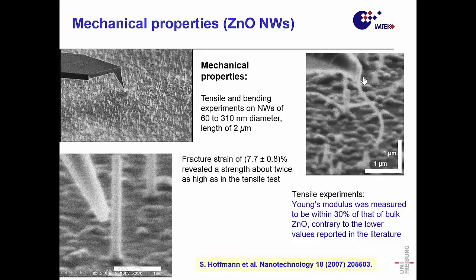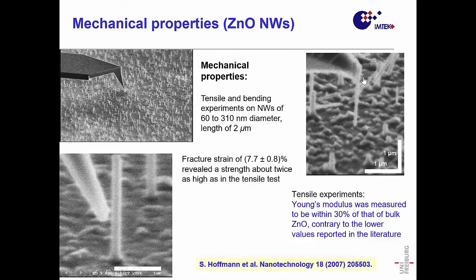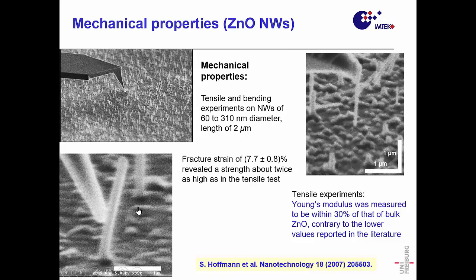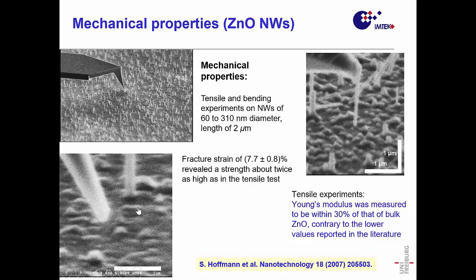And just remember, it's a single crystalline nanowire. It's, I think, amazing. By doing this experiment and then a video clip of that, you can actually then calculate the mechanical properties of these nanowires. Please take care to also keep in mind that your tip has mechanical properties. And so what we measured is that the mechanical properties of these rather ideal crystals are plus minus within the range of the theoretical limits.